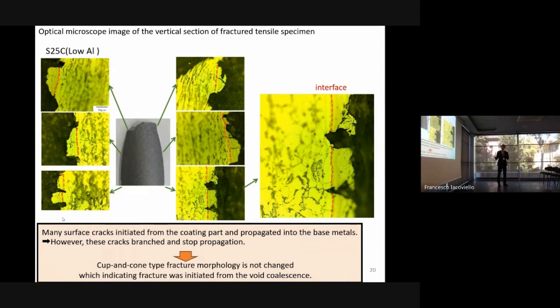Okay, this is the macroscopic morphology of the ruptured tensile test specimen. This is a cup and cone fracture. There are the coating part, the interface, and the base metal. Many surface cracks initiated from the coating parts and propagated into the base metal. However, these cracks branched like this and stopped propagating.